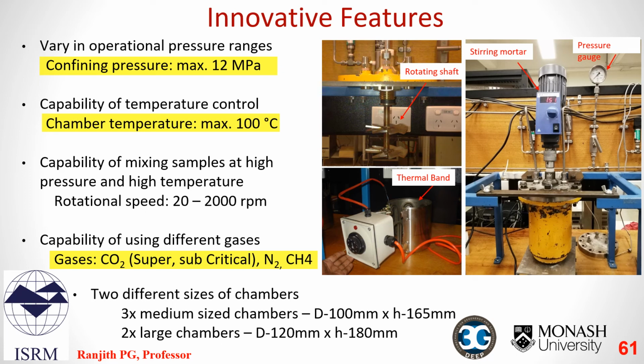The stirring motor and the rotating shaft help us to enhance the reaction rate by mixing the sample with the pressurized gas or liquid. We can make direct measurements of temperature and pressures using thermocouples and pressure transducers. Also, samples are taken at time intervals for chemical, mechanical, and image analysis.